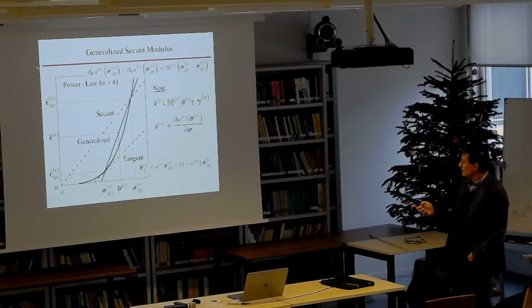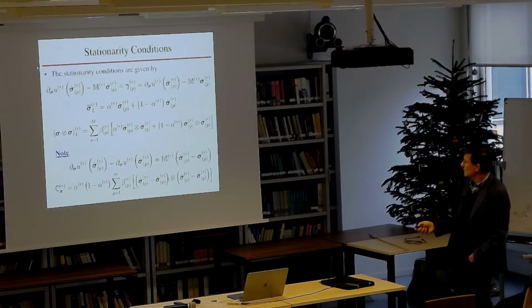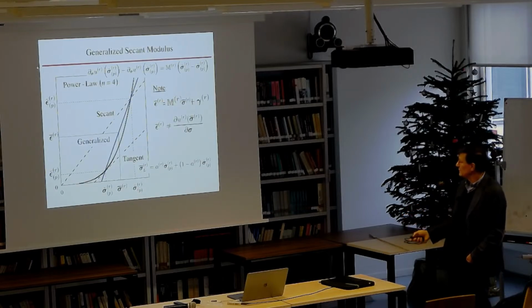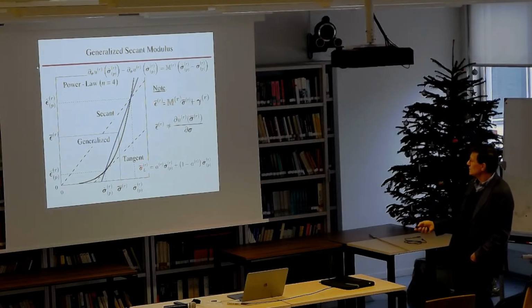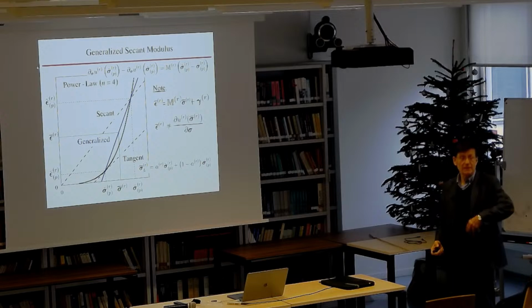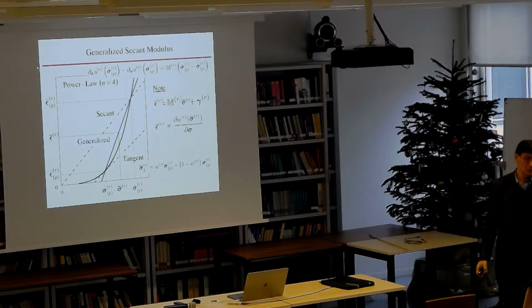And then the other condition tells you that, and this is where these weight factors appear, that the weighted average of these interpolating points, sigma check and sigma hat, should be related to the average stress in the linear comparison composite, which I told you I can